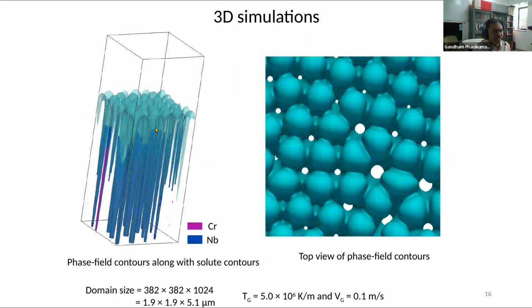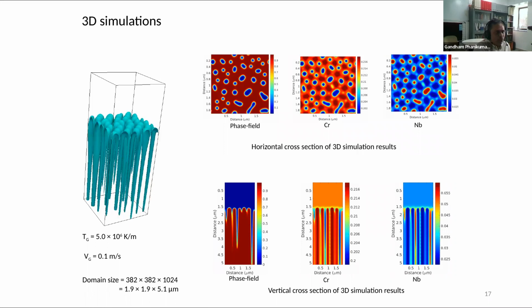And you can then look at them to see how the islands of these compositional contours actually lead to some kind of a lock-in of the phase formations, which we related to, let us say, Laves phase formation at such locations when the chromium and the niobium content is high. Now, that's a clue that we can use these simulations to start predicting the phase formation. So we will do that. Okay, so we have validated these, and we will try to do that.